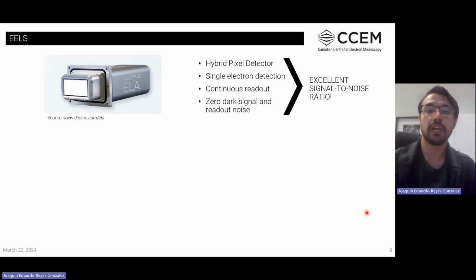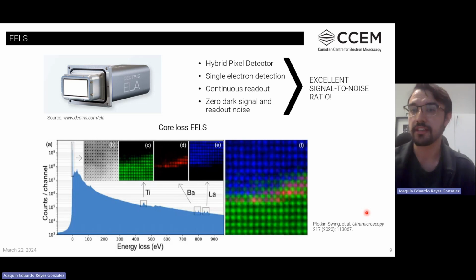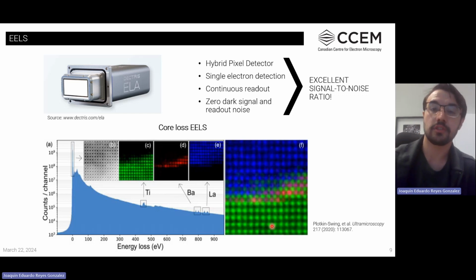So hybrid pixel detectors overall have shown great performance in core loss EELS, and in particular, the ELA has further improved the quality of the data you can acquire in this region. So here, for instance, we have an example of a barium strontium titanate interface over an LSMO substrate, where atomic resolution elemental core loss EELS was performed. First, directing your attention to the EELS spectrum, this would be the result of what is detected on the ELA. You can see that we can have the zero loss peak with really high counts, and we can clearly identify different ionization edges that are not noisy. They are easily seen just by looking at the spectra.